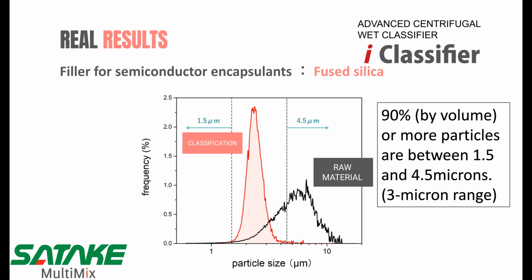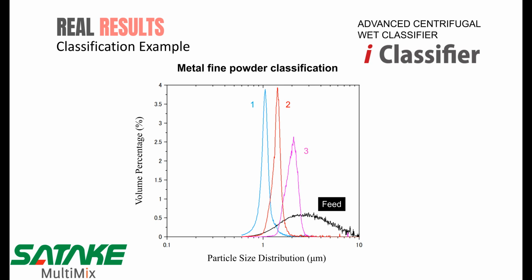Real results continue. This graph shows the particle size curve for the previous example. 90%, by volume, or more particles are between 1.5 and 4.5 microns, only within 3 microns, are collected after the coarse, fine removing process using i-Classifier. This is another real result. Metal powder wet classification data are shown. Metal powder is a high dense material, which could shift the cut point finer, such as 0.4 to 9 microns.